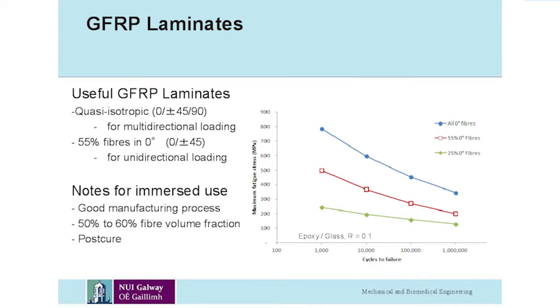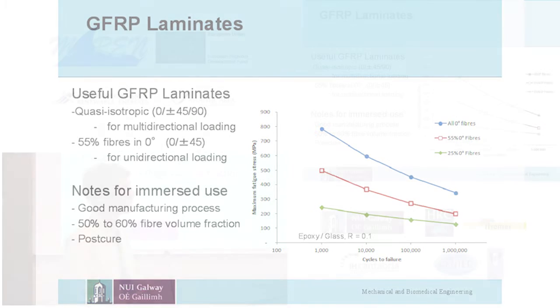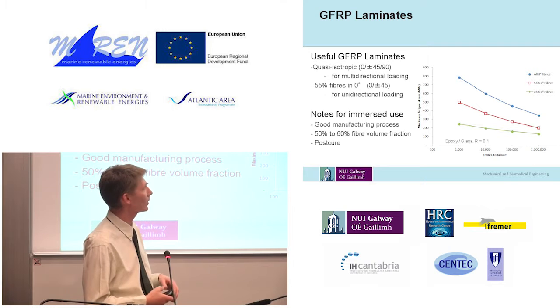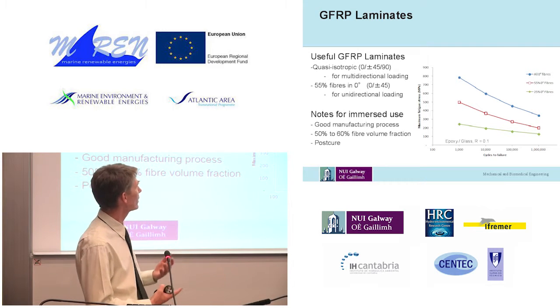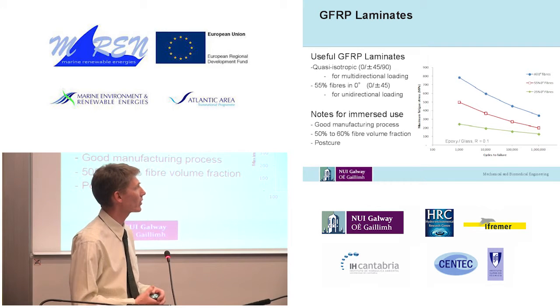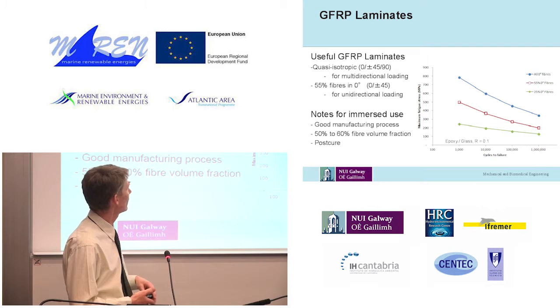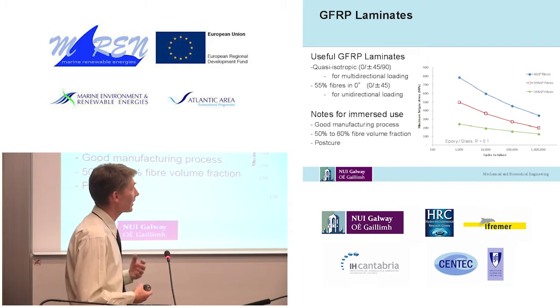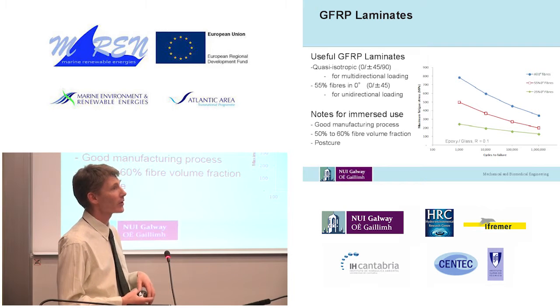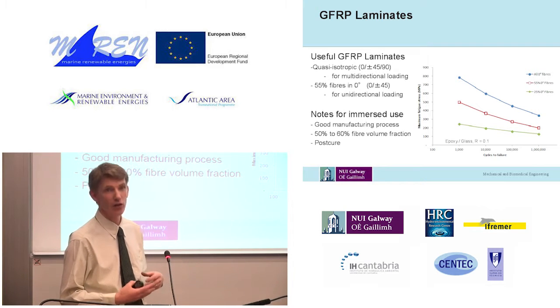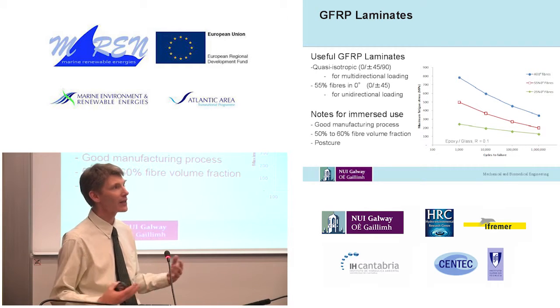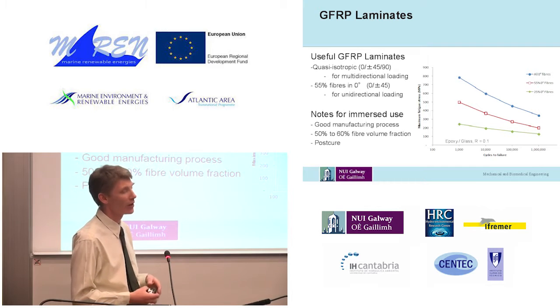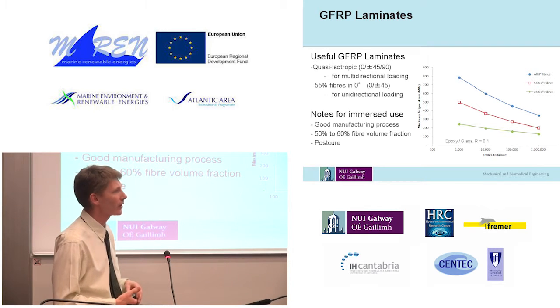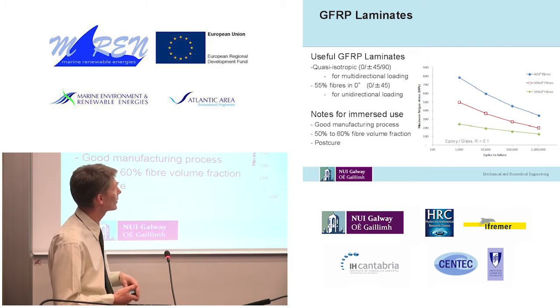So the individual plies of glass fibre are very strong in the fibre direction, but they're quite weak perpendicular to that. So invariably, for most applications, we end up laminating them with the fibres in various directions in order to get a useful material. The only thing about that is that if you go to do design using those materials, it can become kind of daunting. There seems to be an endless number of possible permutations and combinations. So I've put a couple of popular laminates up here so that we could discuss them.